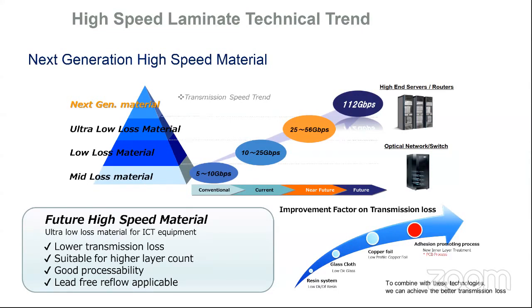The older systems, when you say epoxy has tended to stick to everything, they're not really a problem. It's the high functionality, high speed, low loss materials that are not necessarily an epoxy. They could be an epoxy blend, but now we're relying on less mechanical adhesion properties and more of a compatibility from a chemical standpoint, where we have silane coupling agents or different treatments from different chemical suppliers that have an affinity for improving the wet out of the high speed, low loss resin systems to itself. So that's really where our focus needs to be. Interesting. All right. Well, thank you.